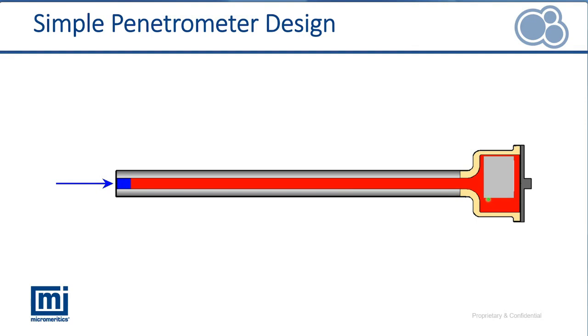And if we then, at the end of the analysis, when we filled all the open pores with mercury, we can calculate an apparent skeletal density by correcting the bulk volume for the total intrusion volume of this sample. So the way we determine the volume intruded, as we apply pressure, up here shown in blue, we will push some of the mercury into the pores, and some of the mercury then will move from this capillary stem into the bowl, into the sample.